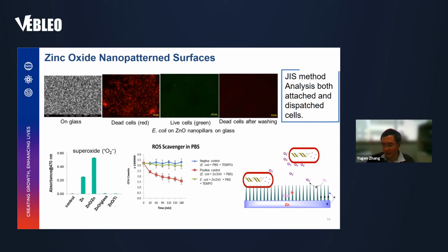For the mechanism, as I show here, this zinc oxide nanoneedles on zinc have multiple mechanisms. Firstly, they can penetrate the cell membrane by this nanostructure. At the same time, through electron donation to zinc oxide, they can also reduce oxygen to superoxide radical. So this radical will kill the remote bacterial cells. This has been proved by this superoxide measurement, and you can see zinc oxide on zinc actually gives much higher superoxide as compared to others like zinc oxide on glass, on titanium, or zinc foils. And we also did this ROS scavenger experiment showing that when the scavenger is added, the antimicrobial activity disappeared, which further proves this ROS mechanism.